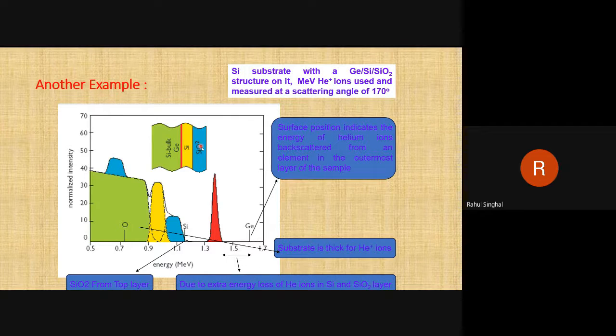But the mass of oxygen is much lesser than silicon, although their position in the sample is the same. Suppose their mass difference is also very small, then the peak of the oxygen should come near to the silicon peak. But because the mass difference is too high, and oxygen is the lightest element among these four, the oxygen peak will come at the lowest energy. So this peak is due to the oxygen. Okay, sir. Fine.